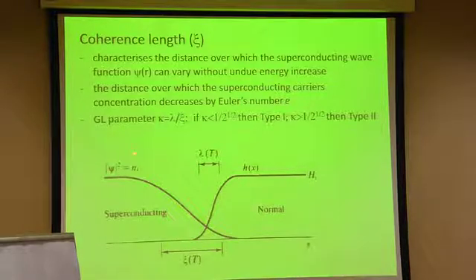In the superconductor, deep inside, we have the maximum carrier concentration, which is proportional to the square of the amplitude of the superconducting wave function. And of course, in the normal phase we do not have any superconducting carriers, so it should go to zero. The distance over which this goes from the maximum to zero is the coherence length. And we see also that lambda, the penetration depth, is the length over which the external field drops to zero at the normal superconducting interface.